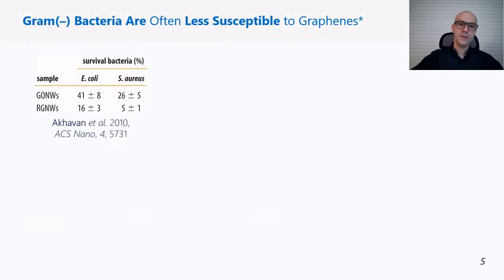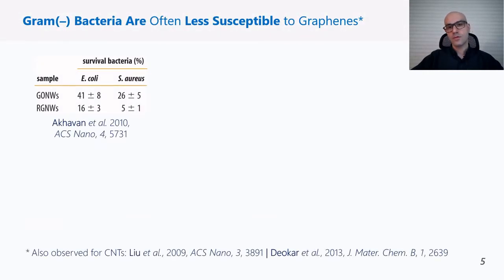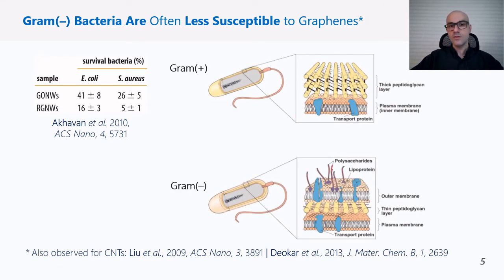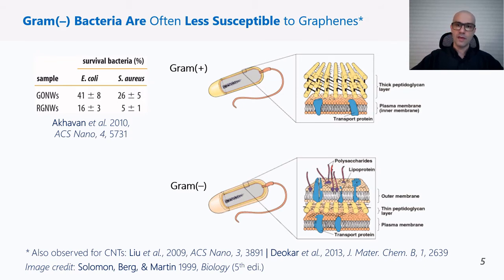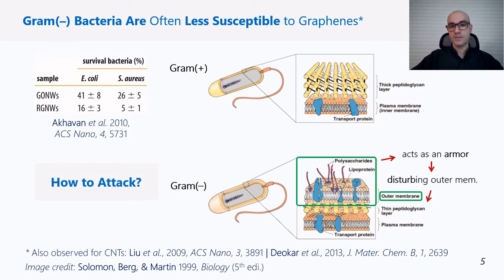I started by thinking about why graphene materials often show lower antibacterial activity against gram-negative bacteria. Here you see a general overview of a gram-positive and a gram-negative bacterial cell. Basically, gram-positive cells have 2 layers in their cellular envelope, a thick peptidoglycan layer and an inner membrane. On the other hand, gram-negative cells have three layers: an outer membrane, a thin peptidoglycan layer, and an inner membrane. We thought that this outer membrane might be the key as an additional armor and decided to attack it.